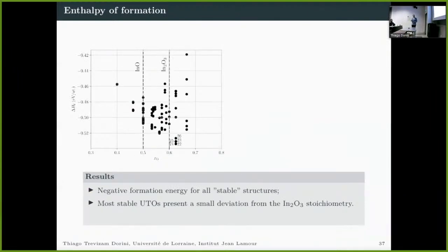After we have chosen which are the best structures to study in detail, we have increased the precision of all our calculations, and we have redone the formation energy for these phases. As we can see, there is a negative formation energy for all these phases, which is very positive for us. That means that all these phases are stable.